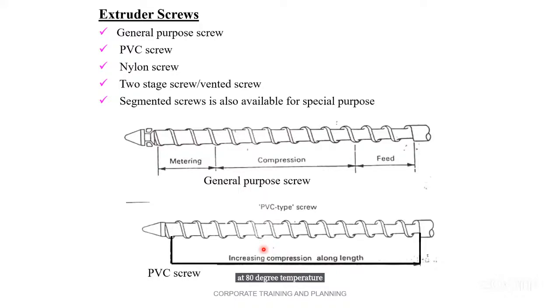But we are doing the compounding of PVC. We are adding plasticizers, stabilizers, extenders, oils, many things, additives. And that's why we can process PVC material maximum up to 200, not more than that. If we exceed 200, then PVC will start to burn. Again, the color will change. But out of fear, people are running the machine at 180, 190 only, not more than that.